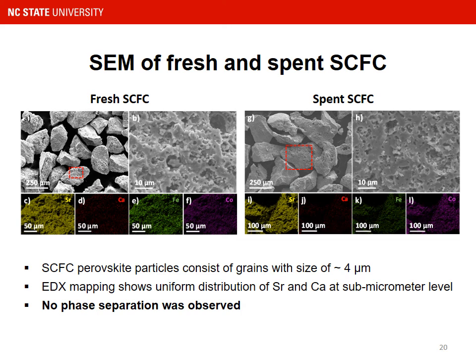The morphology of the spent co-doped sample was studied by scanning electron microscopy. It shows that the sample morphology remains almost unchanged. No sample sintering or phase separation was observed after 100 cycles of redox test.